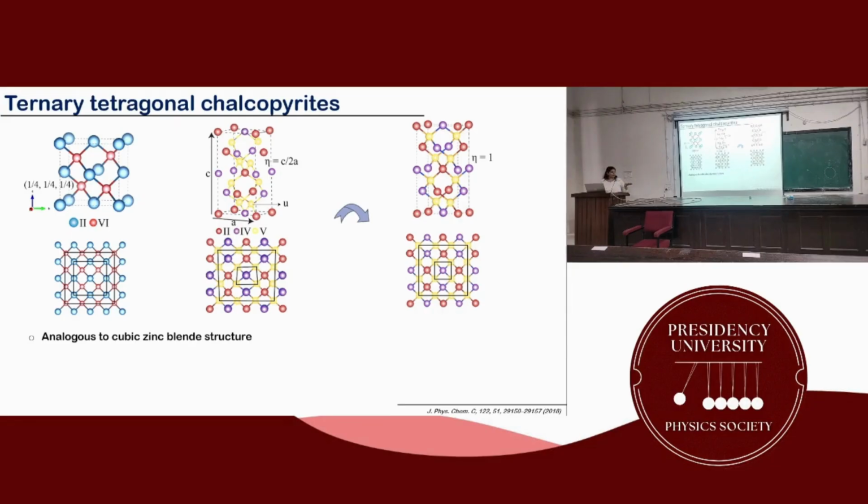Now, is there a way that I can tune the second system? I can move some atoms, do something, and then reach a point where it still has the tetragonal symmetry, but has this kind of pseudo-cubic framework as ZnS. Since that is a lower symmetry tetragonal structure, I expect that the thermal conductivity probably will be lower. But if I can retain this pseudo-cubic symmetry, my electronic transport will be better, right? So I want to achieve this. This is the thing that I want to do.